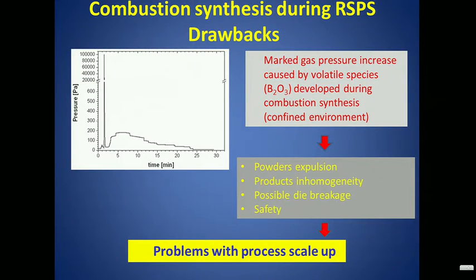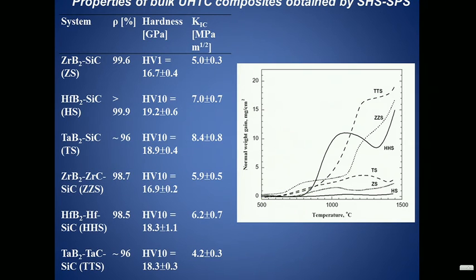The drawback you have when you do combustion synthesis under reactive SPS is the fact that typically you have an increase of pressure. In this case, you have a volatile species, the boria, which is developed during combustion, and you could have powder expulsion from the reacting mixture. You could have product inhomogeneity and so on, and also safety problems and difficulties in scale up. Just to give you here an overview of the main characteristics of these powders we have been producing by a combination of SHS and SPS.